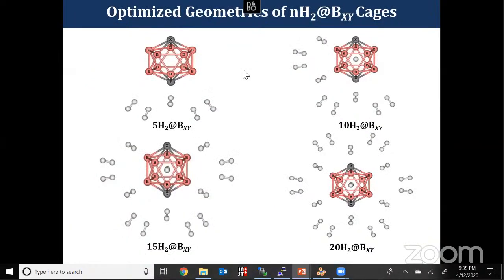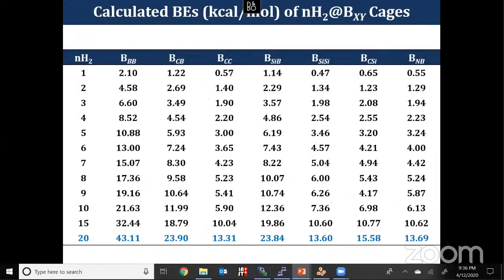As I mentioned earlier, it has 20 faces, so we can store 20 hydrogen molecules. These are the hydrogen-adsorbed clusters. After the binding, I calculated the binding energy for each cluster. From the calculation, the 20-hydrogen-molecule adsorbed complexes show higher binding energy. In that, the 2- icosahedral closo-borane anion has higher binding energy than the rest of the substituted complexes.